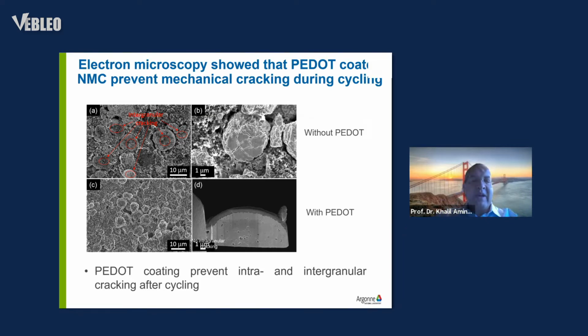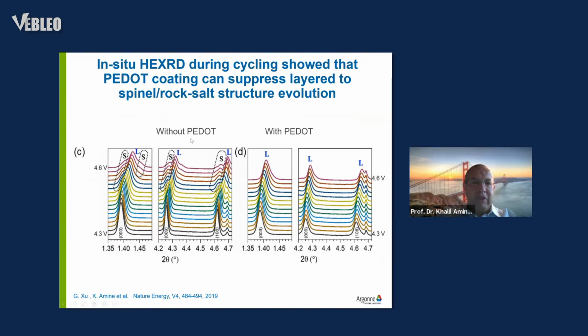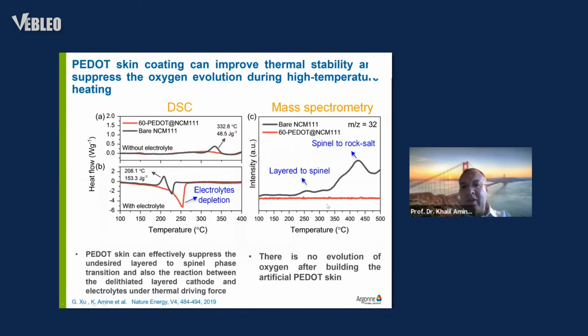We confirmed that by high resolution X-ray at the Advanced Photon Source. When we charge at high voltage, you can see spinel phases formed without the PEDOT coating. However, with the coating or the protection, we don't see any phases forming, and therefore we don't have any oxygen release. We did confirm that by mass spectrometry. You can see that all the way to 500 degrees C, we did not see any oxygen release, while with the bare material, at about 250, you have an oxygen release that created a transformation from layered to spinel.